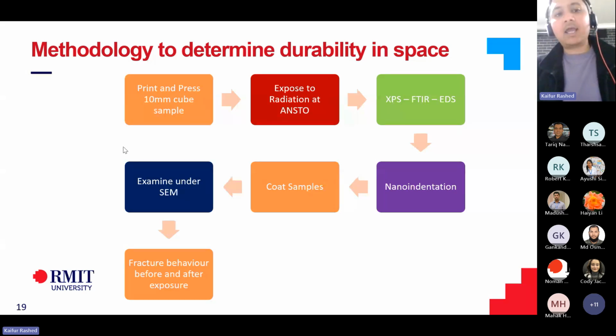So to do that, I printed small samples and I exposed the samples to radiation, and then I studied their chemical properties using XPS, FTIR, and EDS. And I also performed nanoindentation to understand if there's any variation in mechanical properties. And then the plan was to basically, after that, coat the samples and examine under SEM, so that we could understand the fracture behavior before and after exposure.